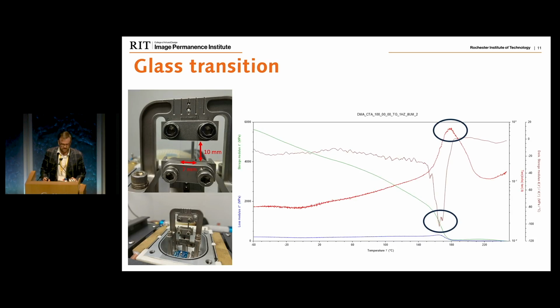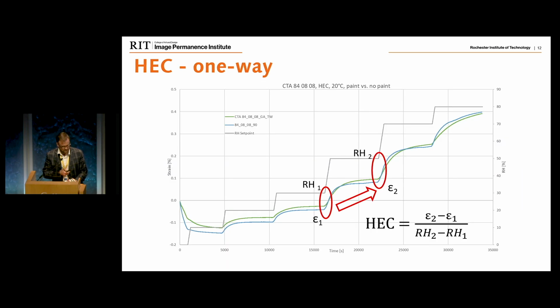Glass transition, again, very simple tests. Here you see one of the samples in the film tension clamps. We are taking glass transition from tan delta and from storage modulus derivative. Nothing unusual. And this is how it is working. And this is how the humidity expansion coefficient curve looks like. So what you're seeing here is the RH. This is the set point. The real RH is never that clean, but the set point makes a nicer graph.